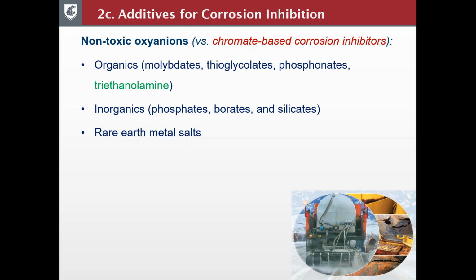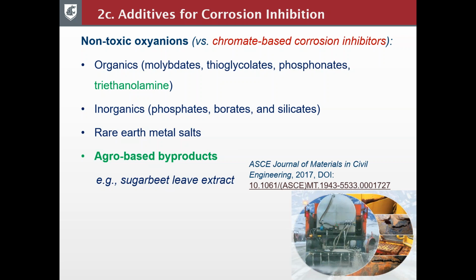Now, inorganic corrosion inhibitors may include phosphates, borates, and silicates. And again, in a later case study, we tested sodium metasilicate. And then yet another group is rare earth metal salts. Now, what about other options? Here's another one, which is the agro-based byproducts. Again, like we mentioned earlier, some of the byproducts tend to not only enhance ice melting performance, but also reduce corrosion. So one recent example was published in ASCE. We used a zero waste process to chemically and then biologically degrade sugar beet leaves to derive green chemicals, and they seem to significantly reduce the corrosivity of magnesium chloride to metals.